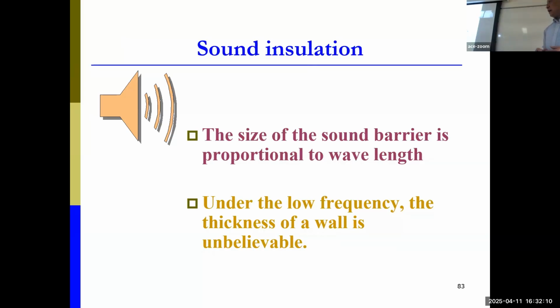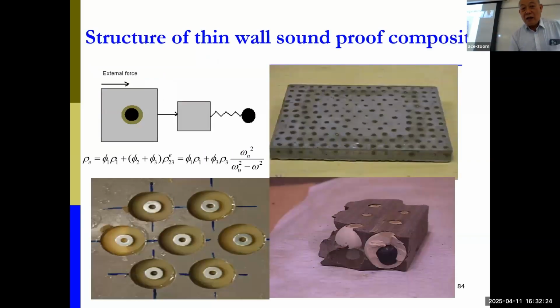We know sound is very difficult to block at low frequency because of the mass law. For low frequency, the thickness of the wall must be increased to block this kind of wave. However, at HKU, we developed, according to physics law, a composite material with different compositions, and we can tune the effective density of the composite material. By adjusting this, we can get almost zero or negative effective density, and then the wave corresponding to that frequency cannot penetrate, according to this physics.